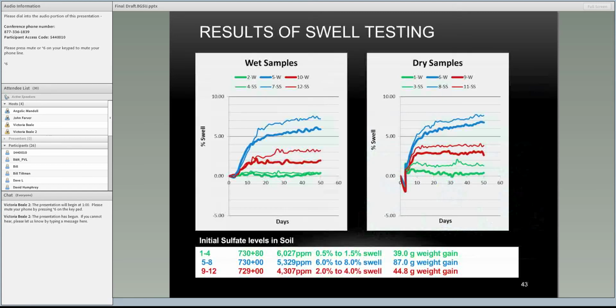And the dry soils swelled slightly better than the wet samples, but not a statistically significant difference. As well, you can see the thin lines on the top are the sodium sulfate samples, and the thick line is the sample from the same stationing, only in water. So you can see that the samples in the sodium sulfate performed slightly better than the water samples. But again, they tended to stay pretty close together.